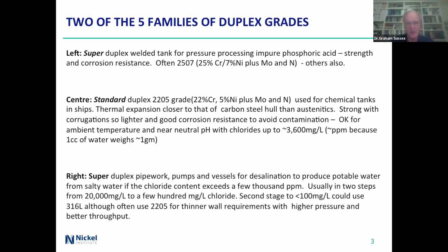Okay, talking about the pictures that I showed first, on the left, there was a super duplex welded tank for impure phosphoric acid. Lots of strength, lots of corrosion resistance, and in that particular case, it was a super duplex. In the center, the tank on a ship made out of 2205, very reasonable match of the thermal expansion with the carbon steel hull. A lot better than austenitics. And it's pretty strong, reasonably light, therefore, because it was thin. And it's got corrugations in it to give you lots more strength. Okay for near ambient temperature with chlorides if you were carrying things with chlorides in up to those sort of limits.